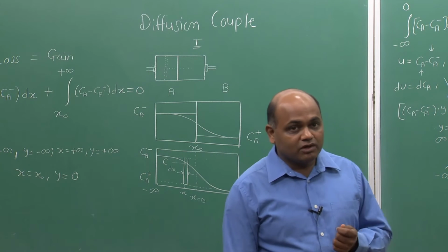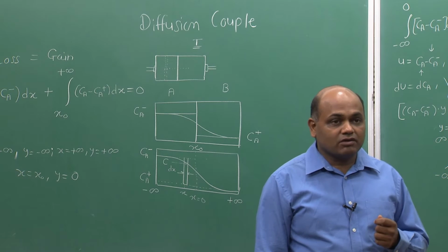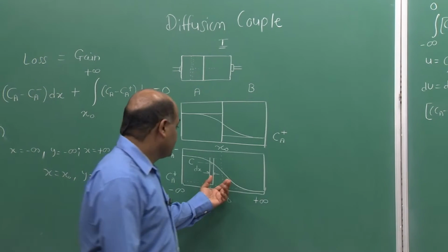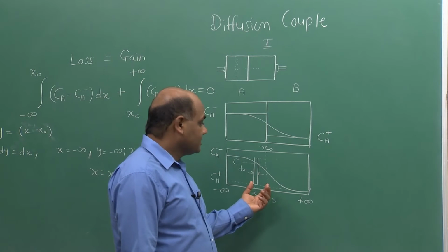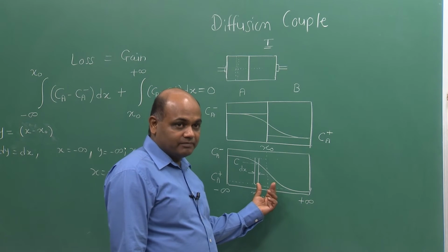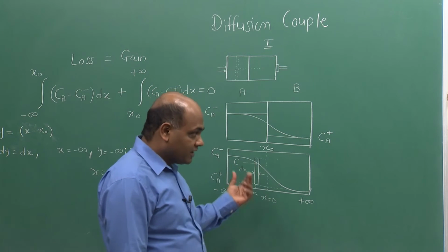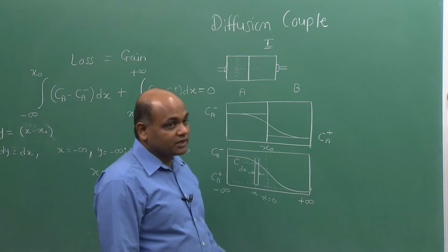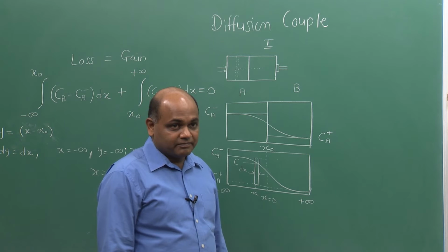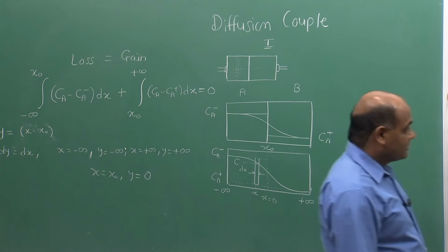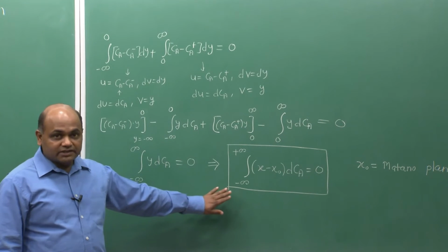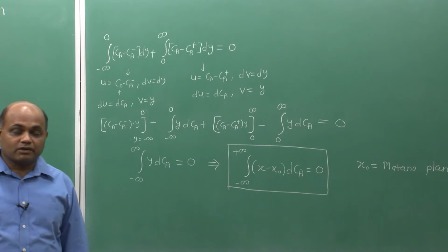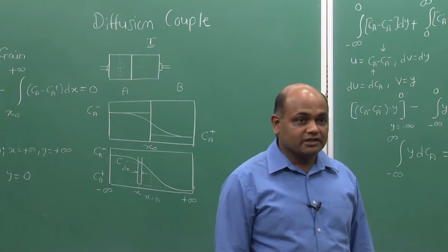If the partial molar volumes of the components is a function of composition, then with diffusion there will be net expansion or shrinkage of the couple, and therefore, each individual component will yield different location of this plane. So, the second condition applicable for this is that the partial molar volume should be independent of composition for each diffusing element.